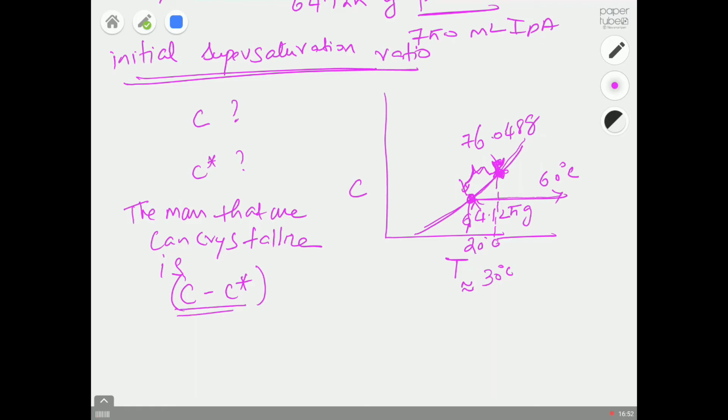So you have to listen to part 1, part 1A, part 1B, part 1C in detail to understand how solubility and supersaturation work, and how to create supersaturation, how to create the driving force that gives you the right condition in order to crystallize a compound. It can be through nucleation or it can be through growth. If you want to go for nucleation, you have to work at the limit of the metastable zone width. If you just need growth, then we have to work under safe conditions. So the theoretical mass that you can crystallize will be equal to C minus C star.